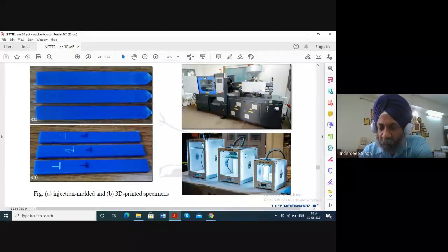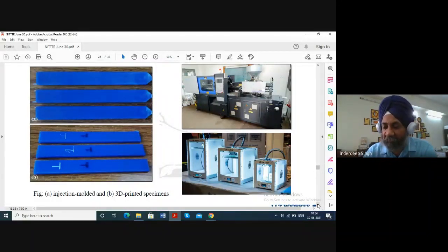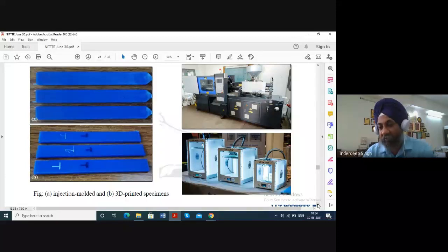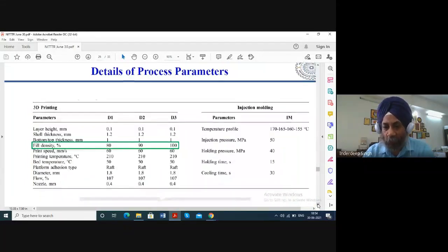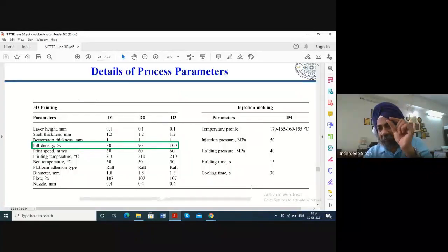But the same fiber spool or the same wire spool we used in injection molding, but here in the hopper, we have to put the pellets. So what we did, we used the pelletizing setup in our lab, which you have seen just after the extrusion process. So the same pelletizing setup we used to pelletize the PLA filament into the pellets, and those pellets were used in the injection molding setup.